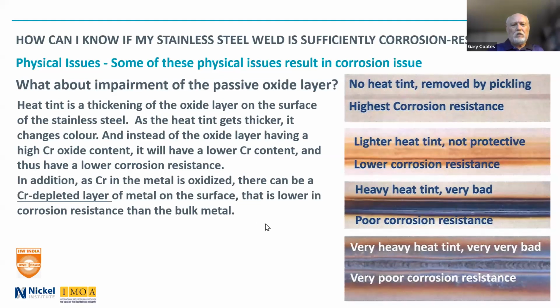Now, in addition, as the chromium in the metal is oxidized during the welding process in the heat affected zone, there can be a chromium depleted layer of metal on the surface that is, again, lower in corrosion resistance than the bulk metal. It is not visible, this chromium depleted layer, because it is solid metal. And if you just remove the discoloration, you have not removed the chromium depleted layer. Now, in many cases, that may not be a huge issue, but in certain cases, it can be a very, very important issue, and you will have to remove also the chromium depleted layer.